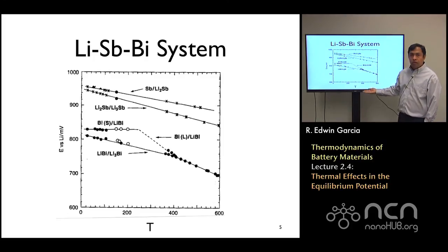For the Li-Bi and Li₃Bi system, you can see that the temperature dependence is always negative, suggesting that really in general, unless we can find a pathological system, the slope becomes always negative or zero, or very close to zero as you see here. And the heat capacity of the system must be very low, so that the curvature—we cannot even tell it apart. It basically becomes very, very flat, almost nonexistent. It is there, but it's hard to tell it apart from this data.